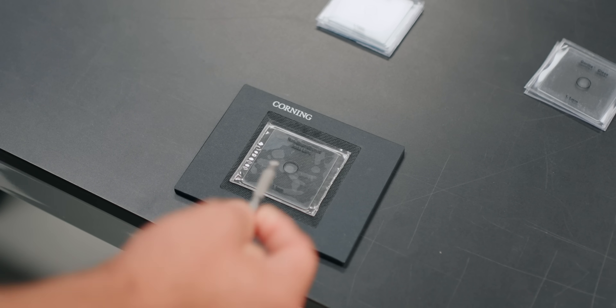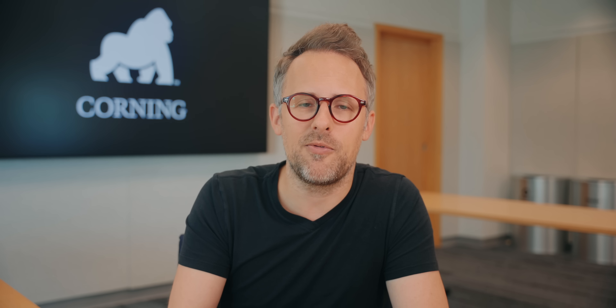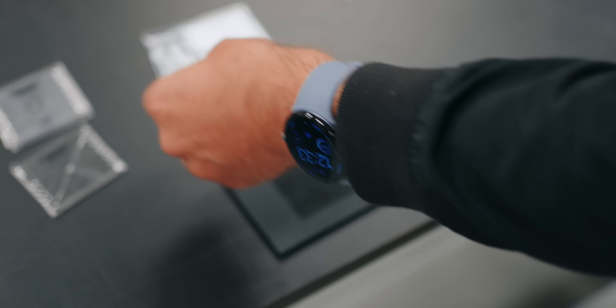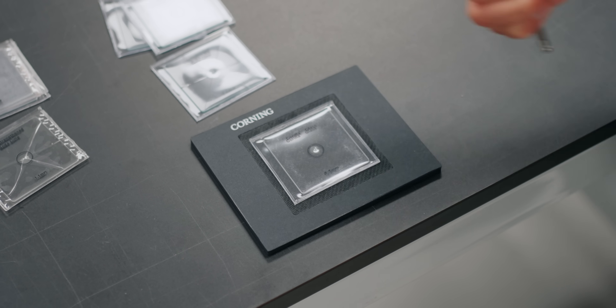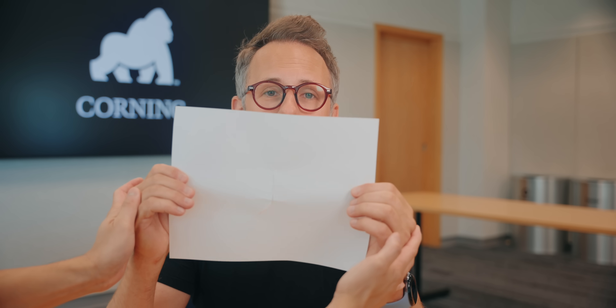Another fun test is the Pen Push, which tests how much pressure you can put on a piece of glass that has a flaw in it. All three panels here are the same thickness and have the same flaw in the middle. When I pushed as hard as I could on the first pane, which is soda lime, it shattered easily. The second pane, which is soda lime glass chemically strengthened similar to the way Gorilla Glass is, took a bit more force to shatter, but it still shattered. The Gorilla Glass, though — I simply could not shatter it. I even used two hands and pushed with all my might, but it would not break. Imagine you're pulling from both sides of a piece of paper: if it's in good shape, it won't tear easily, but introduce a small tear in the middle and it tears much more easily. In the case of Gorilla Glass, the chemical strengthening is similar to someone holding your hands back, preventing you from easily tearing the paper — flaw or no flaw.